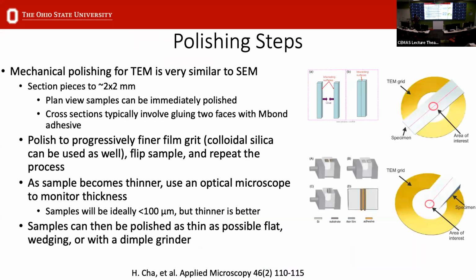With polishing, I mentioned wedge polishing, where you would change the angle on your tripod to have a wedge-shaped sample where the edge of your specimen is the thin part. One other technique that was historically and still is commonly used is dimpling, where you use a grinder to thin a circular region in your region of interest, and that will thin down that area and allow you to target that area for argon ion milling. As I mentioned, you would typically start at a higher grit film, work down to a grit such as 0.1 micron diamond, do colloidal silica, and once you have that sample thinned down, you attach your grid, and then it's ready for argon ion milling.